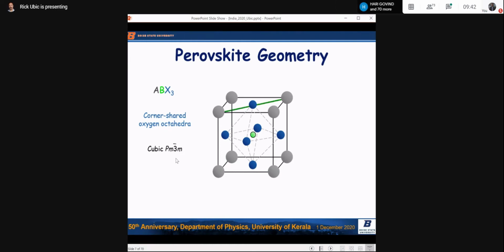Okay. So if we want to describe the lattice constant of this cube, we have several ways of doing it. We first assume that anions and cations are in contact. And if that's the case, we can draw a face diagonal this way. And remember, that's the A site. That's the X site. So we have two AX bond lengths, or 2R_A + 2R_X is equal to, just from Pythagoras, the square root of 2 times the lattice constant, right? That's the hypotenuse of this triangle. I hope you can follow my cursor there.